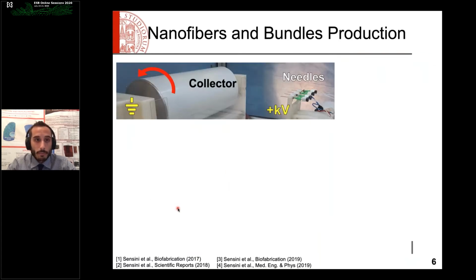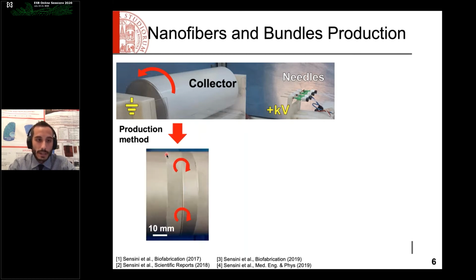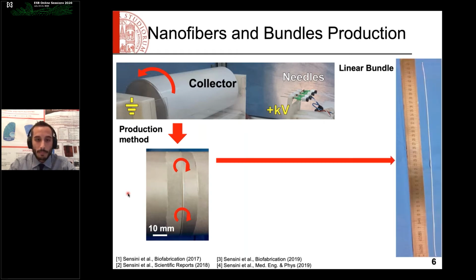So, starting with a bottom-up approach, after the optimization of the nanofibers and polymeric solution, I used an electrospinning machine with a rotating drum collector with which I aligned the nanofibers along the rotational axis of the drum, producing nanofiber mats that I manually cut into stripes and wrapped up on the drum, obtaining electrospun bundles with different morphologies.